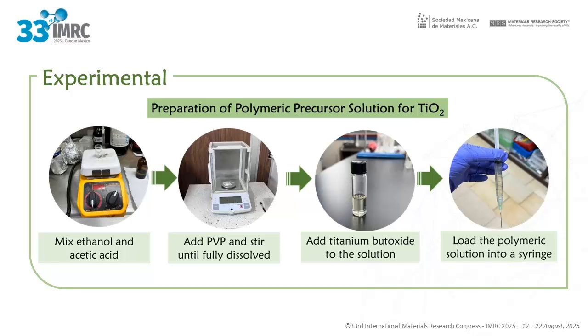To perform coaxial electrospinning, the first step is the preparation of the polymeric solutions. For the titanium oxide solution, first 2.5 milliliters of ethanol and 1 milliliter of acetic acid are mixed. Then 0.70 grams of PVP are added and stirred. After that, 1.75 milliliters of the mixture are taken and 0.75 milliliters of titanium butoxide are added. Finally, the solution is sonicated and loaded into the syringe.